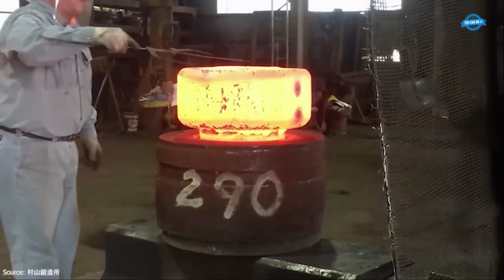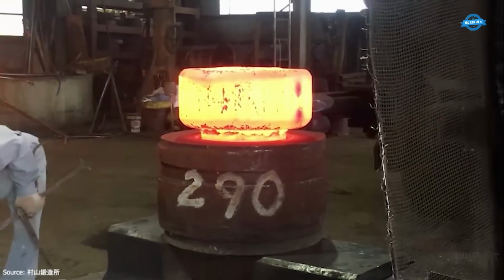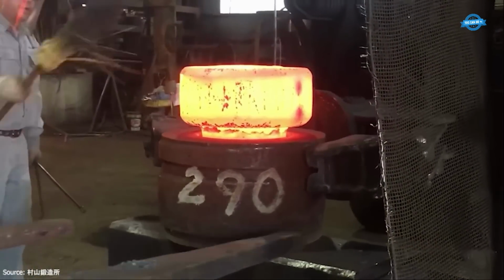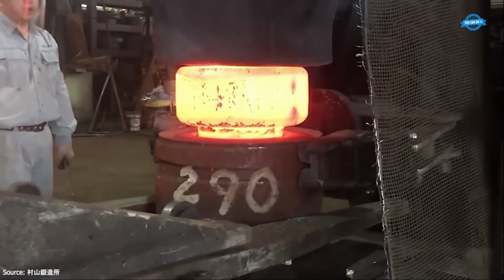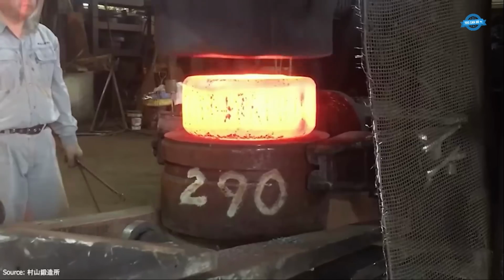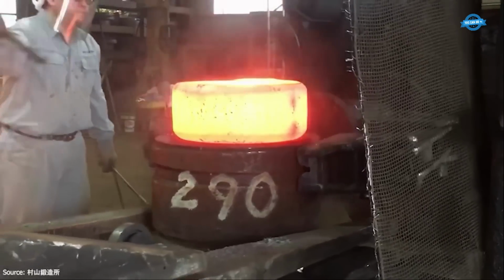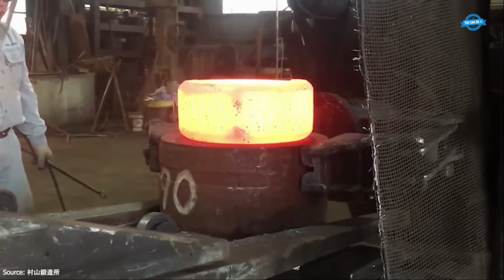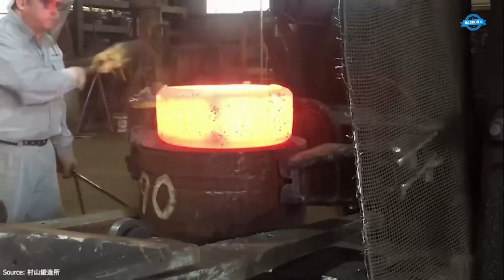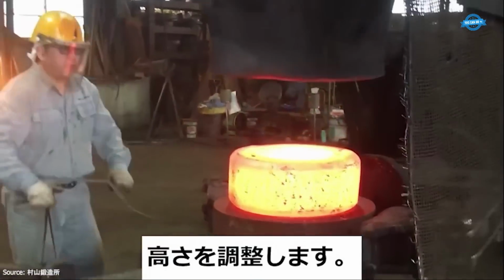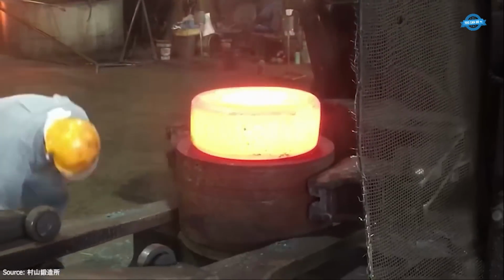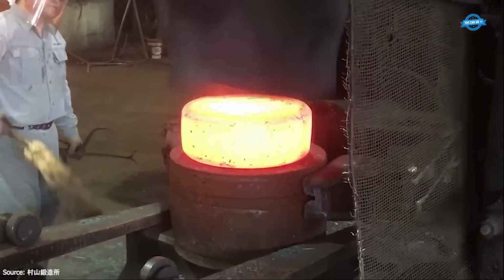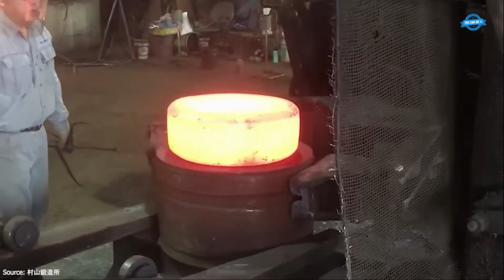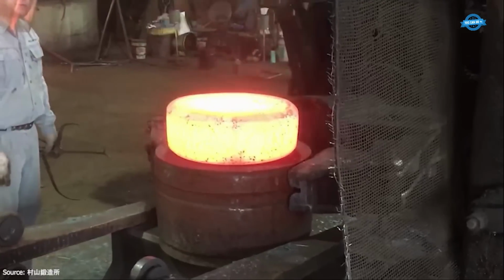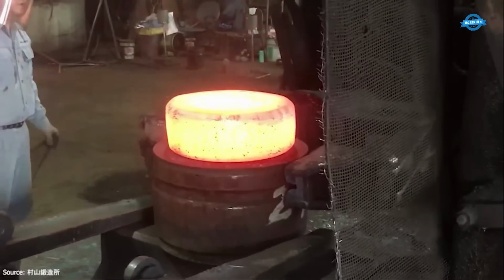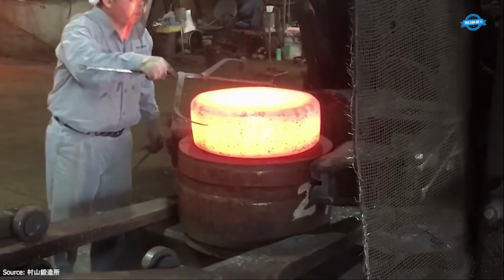The forging enters the critical adjustment phase. The piece's dimensions are refined. Operators monitor both the diameter and height, ensuring that tolerances are met precisely. In Murayama's operations, dimensional tolerances for large couplings are often held within plus or minus 1 millimeter. Multiple measurements are taken during this phase, using calipers and template gauges. If needed, slight reheating in the furnace may be performed to maintain optimal forging temperature during the final adjustments.